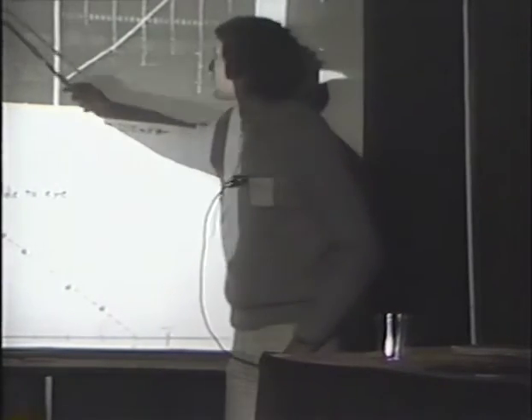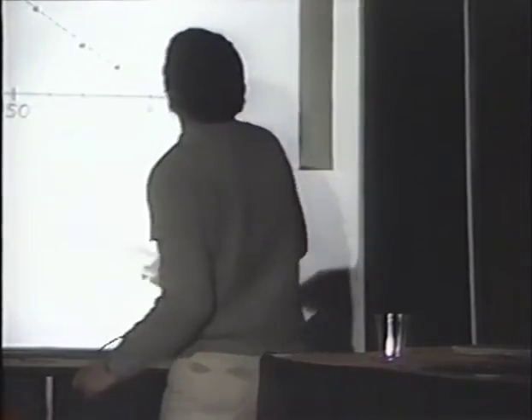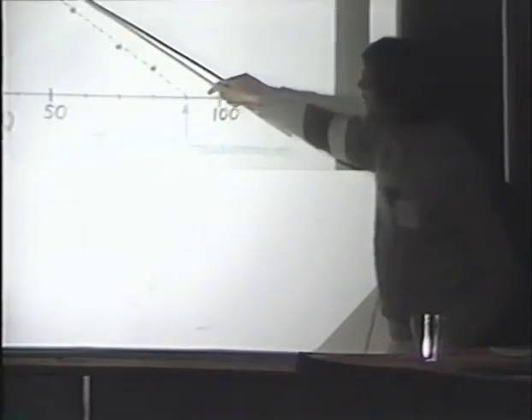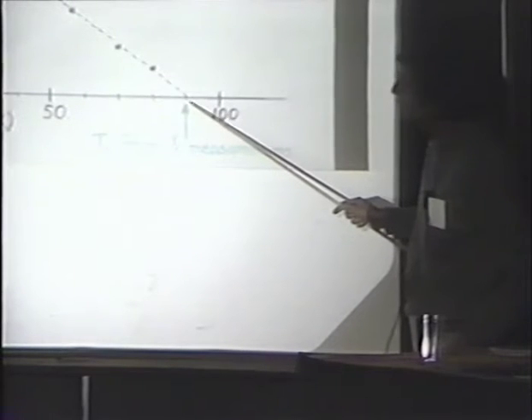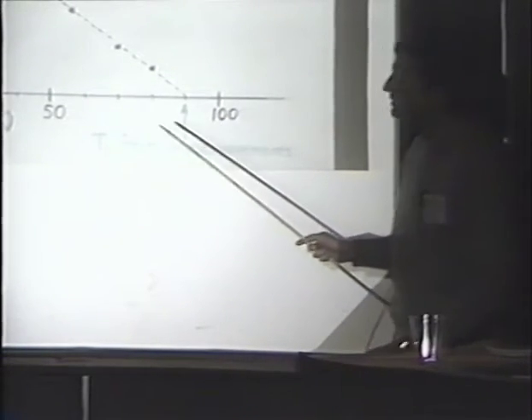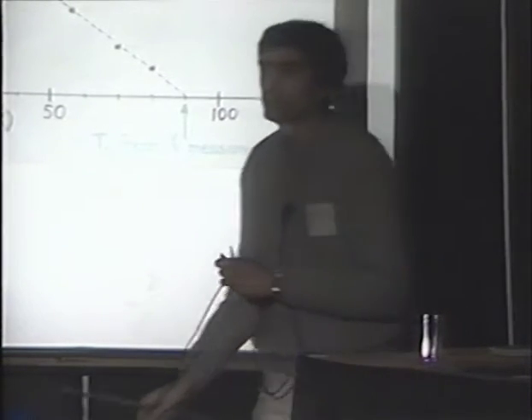As you go up to higher temperatures, this is the yttrium compound, this washes out, but we can still sort of resolve it here. If I plot this critical current versus temperature, we have these points. We draw a straight line down to here, and it intersects 90 Kelvin, which is the TC that we get from susceptibility measurements.